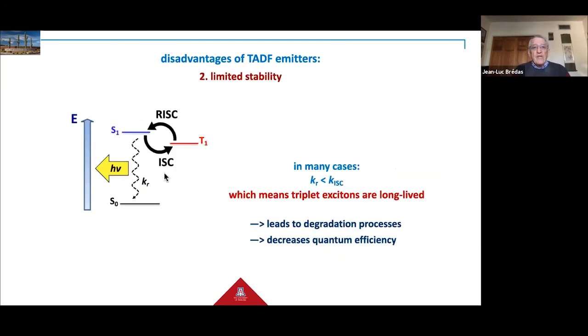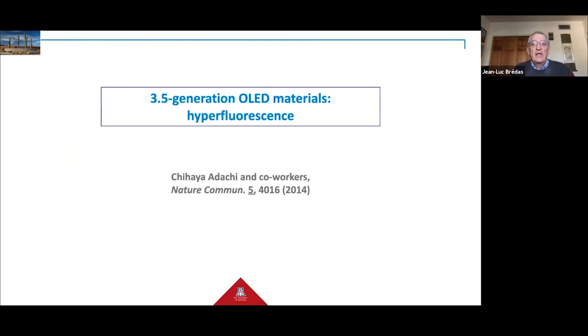Also, in many instances, the rate of radiative decay is slower than the rate of forward intersystem crossing, which recycles triplets. And so we get long-lived triplet excitons, which can lead to degradation processes and decrease the efficiency. And that's the reason why Chihaya Adachi then proposed the 3.5 generation of OLED materials based on hyperfluorescence.